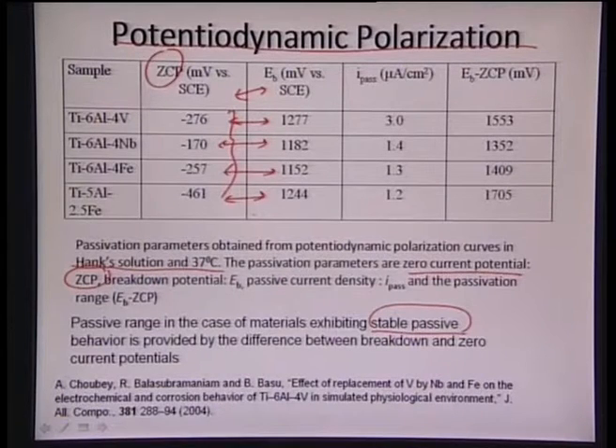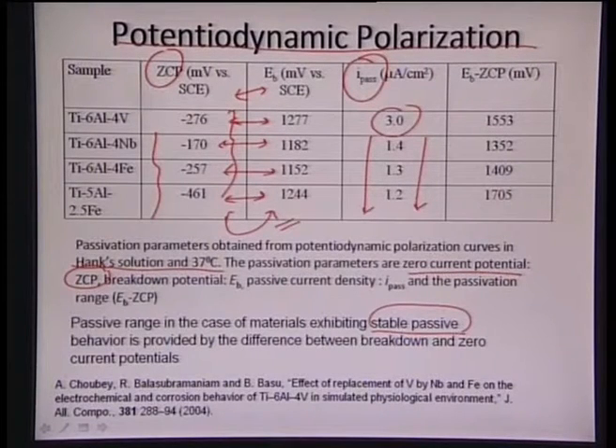So based on that, we can also see the approximate passivation current density, which is very high for titanium 6 aluminum 4 vanadium, but it is marginally, approximately half, as compared to the other alloys. So that's what is being observed here, that the passive range in the case of materials which have a very stable passive behavior is basically given by the difference between the zero current potential and the breakdown potential. That's what we are seeing out here, that the breakdown potential is very high for titanium 6 aluminum 4 vanadium, but it's approximately comparable for other alloys as well. So all these results are not so drastically different, but they are all comparable with one another.